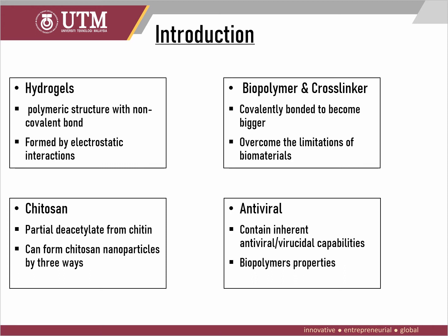Chitosan is made from chitin, which goes through the process of partial deacetylation. To form chitosan nanoparticles, there are three ways of chitosan cross-linking method, which are chemical cross-linking, radiation cross-linking, and physical cross-linking. For the chemical cross-linking method, chemical cross-linkers are glutaraldehyde, genipin, glycol, dextran sulfate, 1,1,3,3-tetramethoxypropane, among others. Next, the radiation cross-linking method does not need heat or catalyst, which means no additional toxin is involved.